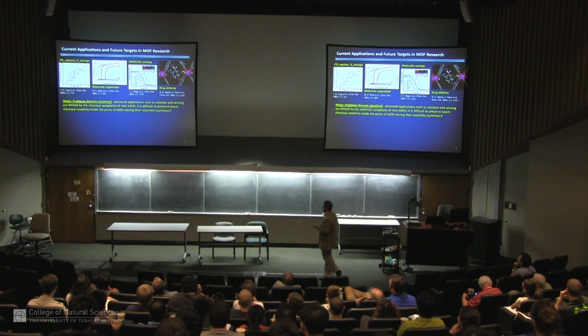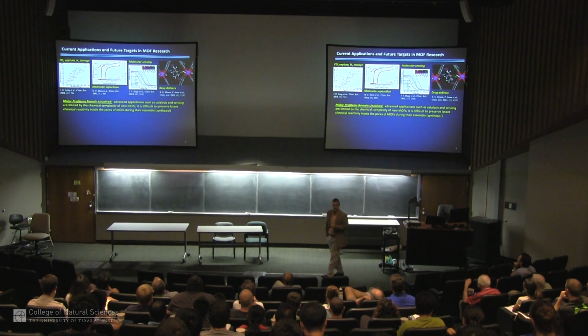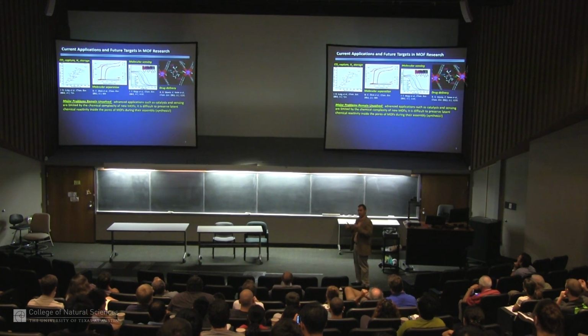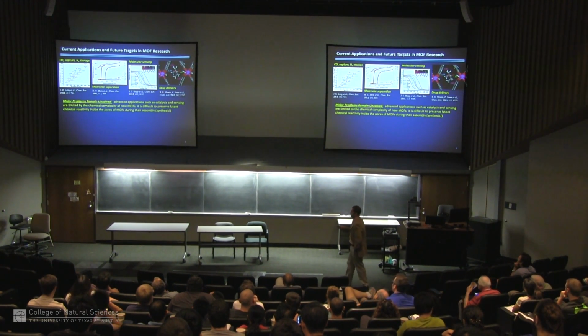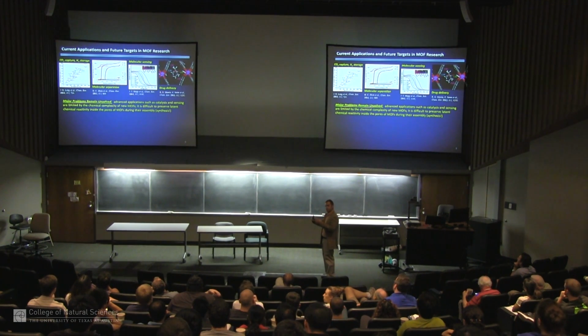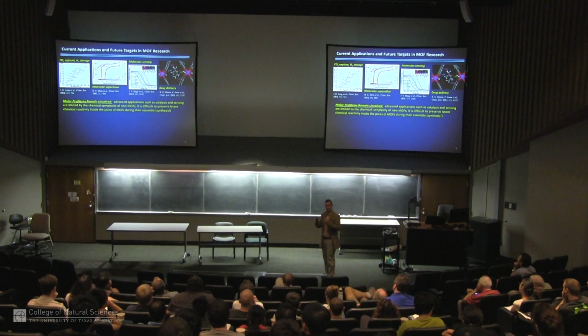But there are still lots of questions to be answered in this field, which is what we're trying to play a part in. And one of the questions is related to catalysis with these materials. And so we're really limited at this point by how much chemical reactivity we can engender into a metal organic framework that we can have inside the pores to allow us to do advanced reactions such as catalysis. And the problem is really that when you assemble one of these MOFs, and we do this in solution, most of the bonding and the chemical reactivity is taken up in the formation of the framework. And so keeping some behind, having some latent reactivity, is fairly difficult. You need to think about strategies to do that.